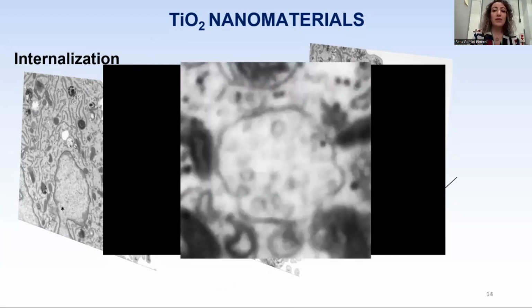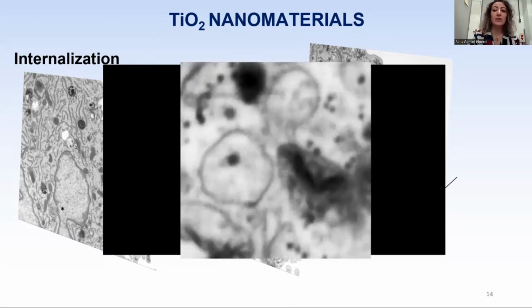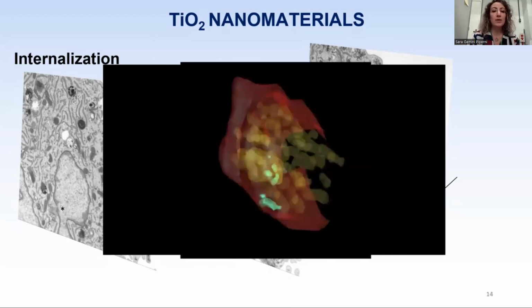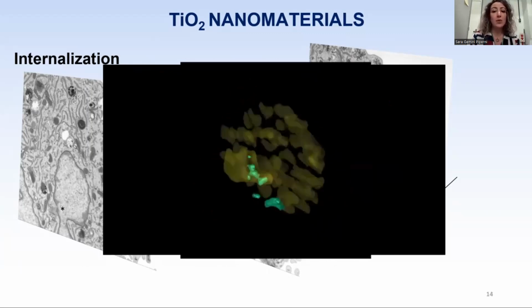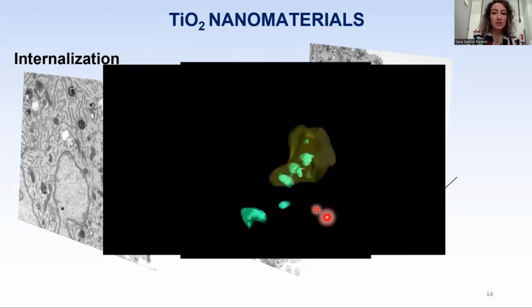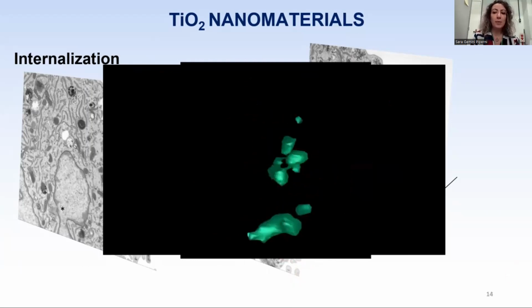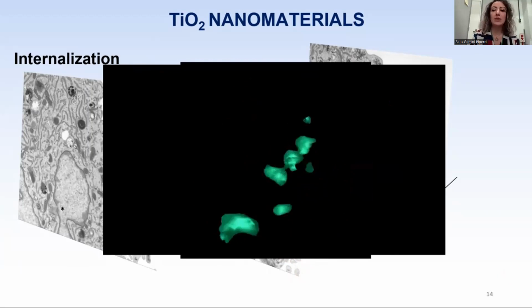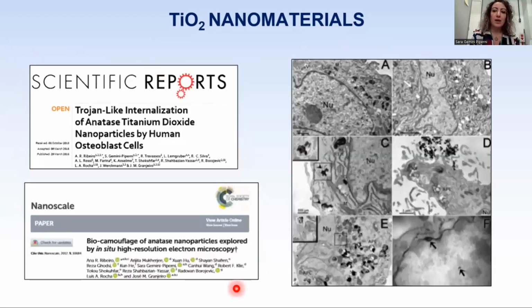So with the higher magnification, we see that nanoparticles are present in intracellular multivesicular bodies, colocalized with the exosome and cell waste. And we found that titanium nanoparticles can be internalized because they are covered with a rich protein corona that is rich in calcium and phosphate, and that is able to mask the titanium. These findings are published in these 2 papers in Scientific Reports and Nanoscale journal.